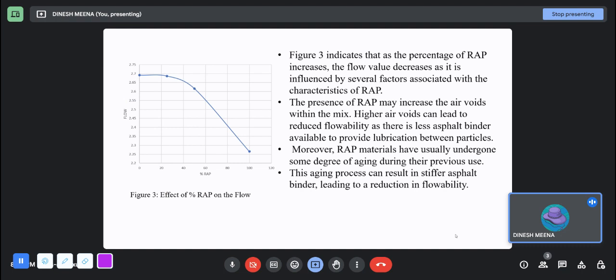Then figure 3 shows the effect of percentage RAP on the flow. Figure 3 indicates that as the percentage of recycled asphalt pavement increases, the flow value decreases, as it is influenced by several factors associated with the characteristics of RAP. The presence of RAP may increase the air voids within the mix. Higher air voids can lead to reduced flowability as there is less asphalt binder available to provide lubrication between particles. Moreover, RAP materials have usually undergone some degree of aging during their previous use. This aging process can result in stiffer asphalt binder, leading to reduction in flowability.